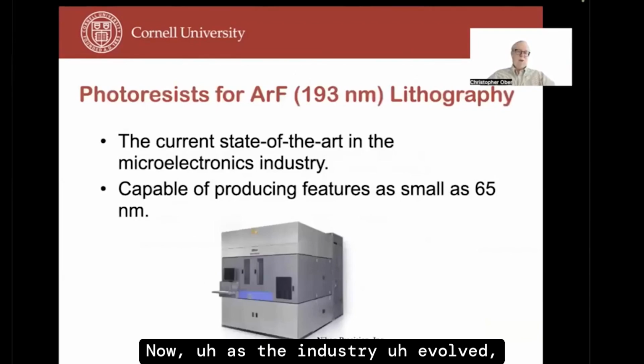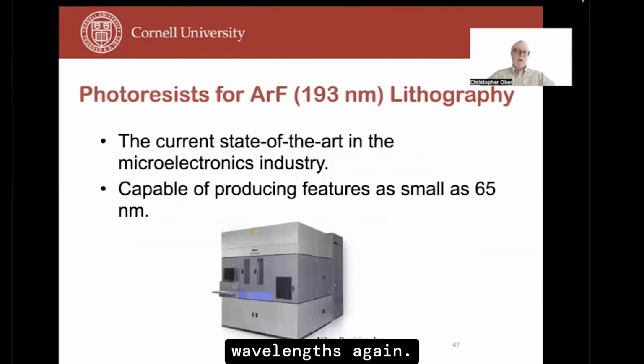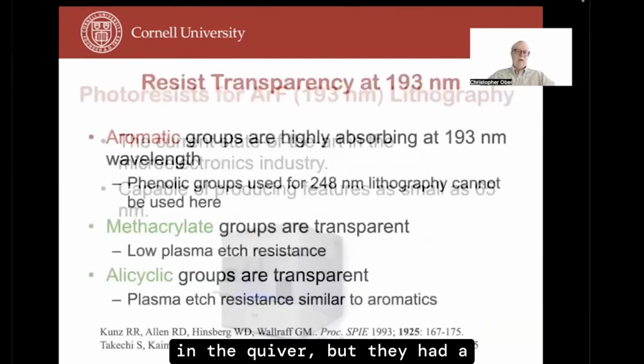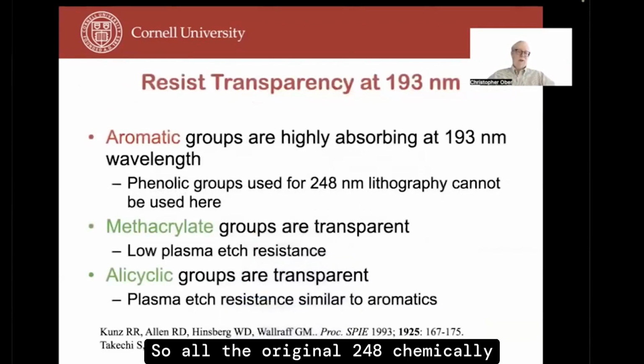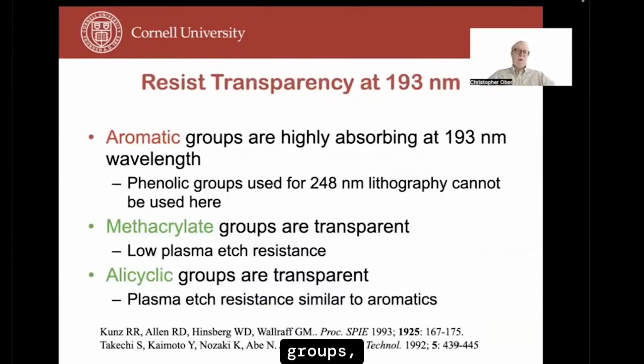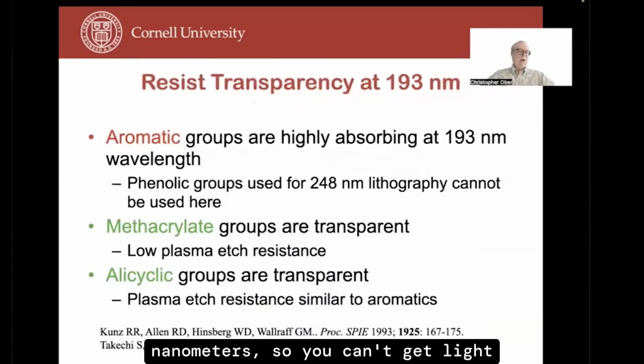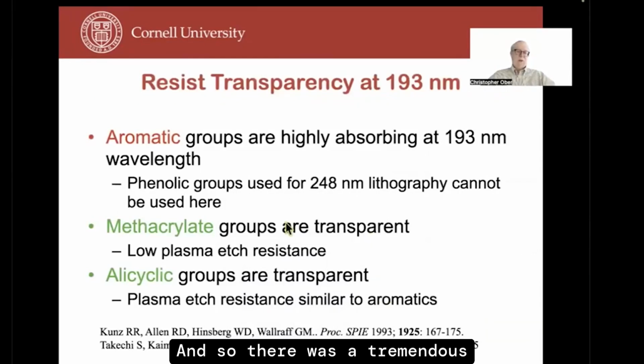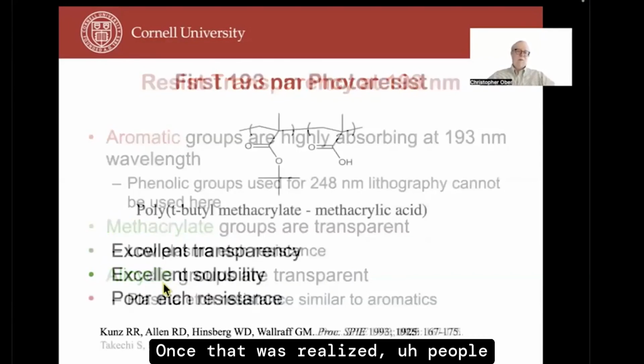Now, as the industry evolved, they needed to go to shorter wavelengths again. So they had chemical amplification in the quiver, but they had a problem. All the original 248 chemically amplified resists are based on structures that had aromatic groups. Aromatic groups absorb at 193 nanometers, so you can't get light through the system. And so there was a tremendous amount of work to figure out how to make a 193 nanometer resist. And they found that methacrylate groups were transparent at that wavelength, and alicyclic groups were transparent at that wavelength. And you could get your etch resistance, the photoresist resisting etching, through the use of these alicyclic groups. And once that was realized, people were off to the races.